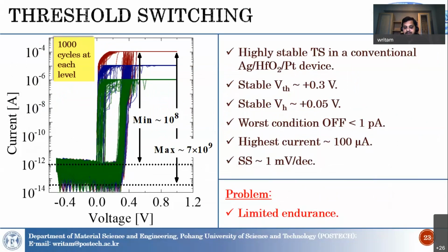Initially, we have this vacancy filament, and then we place the silver in very close proximity to the vacancy. In that process, we basically localize the filament in the structure, and that is the reason for the improvement.